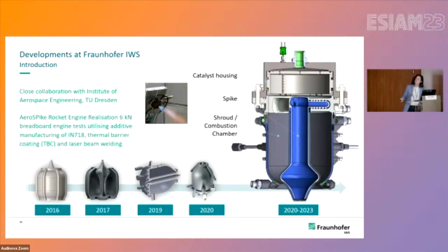In this case, we're not actually experts in the design of such rocket engines, so we started a collaboration funded by ESA with the Technical University in Dresden, the design department for such applications. And this is the, let's say, natural development of our designs. Also, the size is quite different. We started with a quite small first demonstrator, 100 millimeters, and now the actual demonstrator is around 500 millimeters in height. We also changed the post treatment of the cooling channels and heating channels to increase efficiency and to modify the dynamic flow.